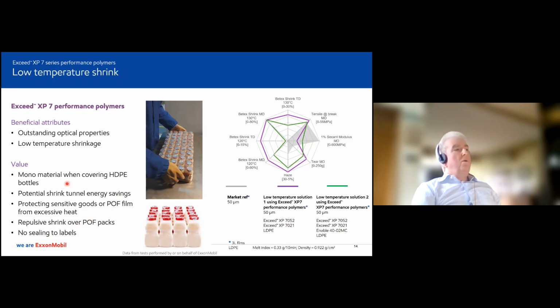Now, if you were even considering putting shrink film around an HDPE bottle as opposed to a polyester bottle, and you're really worried about low temperatures, then this is another type of structure that you could consider. Okay, so again, now we're exploiting the fact that this resin has good shrinking properties at very low temperatures, and is obviously a very good consideration for shrink film.